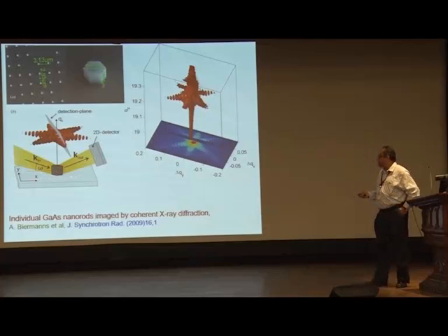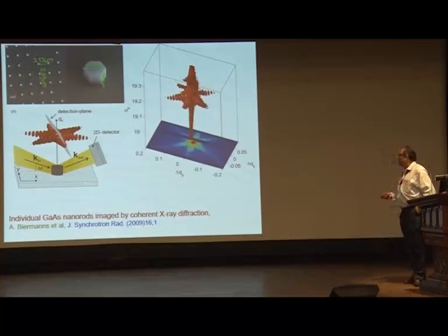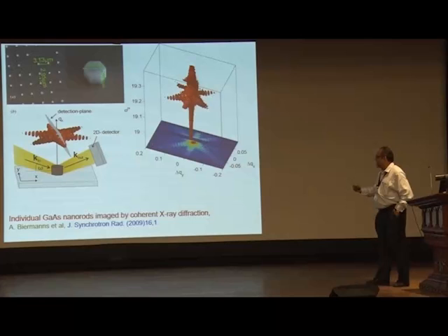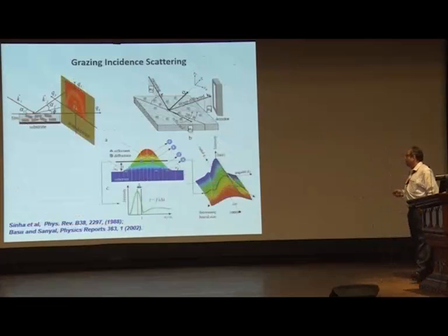That has been solved by putting the sample on a piezo and giving active feedback, so that your measurement is done by shifting the sample continuously, so that it is always on the beam. But the main problem that remains is how to do the diffraction from a tiny object where X-ray scattering is very, very little. So this is our topic.